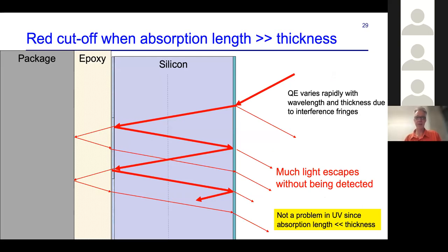This shows what happens when you put long wavelength photons in and they pass all the way through the device and they bounce backwards and forwards in the silicon, and some of them go into the epoxy layer, and you get an etalon effect, variously known as etaloning or fringing. We don't have to worry about that either because our photons get absorbed so close to the back surface that they don't make it all the way through.